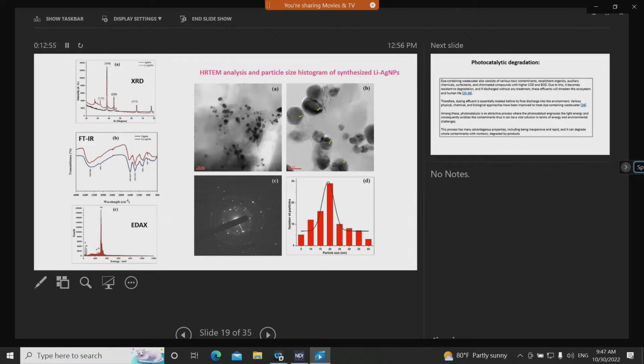And this is the HRTEM analysis, which showed that lignin silver nanoparticles are uniformly monodispersed and spherical in shape. At higher magnification, the dispersed AgNPs showed some fringes in black color, as you can see here, which specifies the different functional groups or chemicals of lignin present on the surface of the synthesized nanoparticles. The SAED pattern exhibited the polycrystalline nature of the AgNPs. Finally, the particle histogram disclosed the average particle size of nearly 20 nanometers.